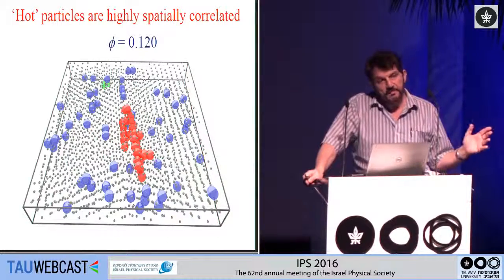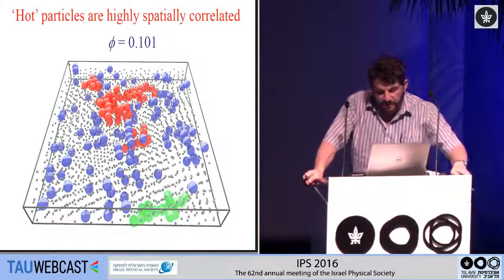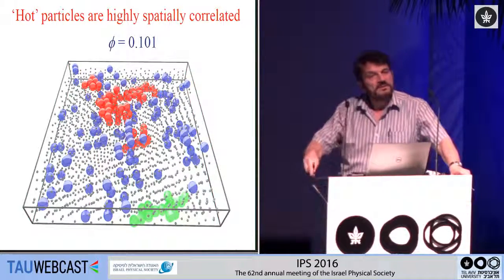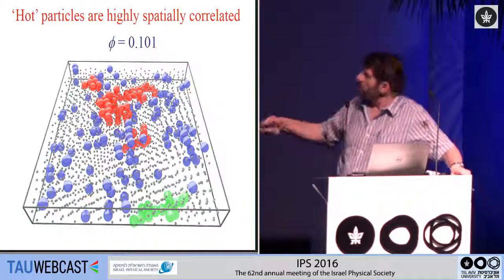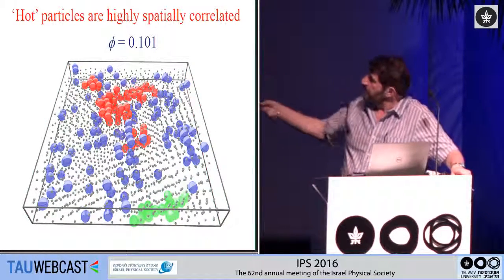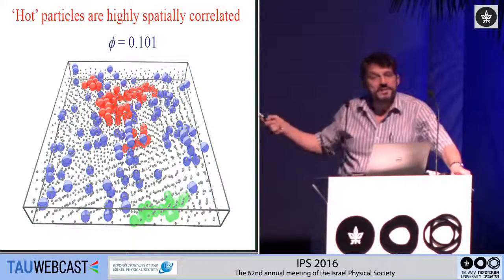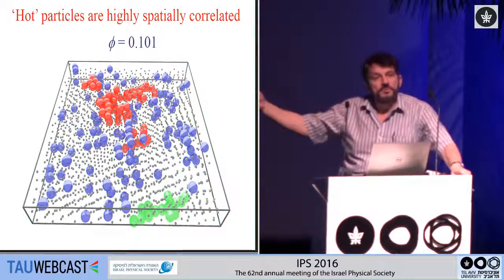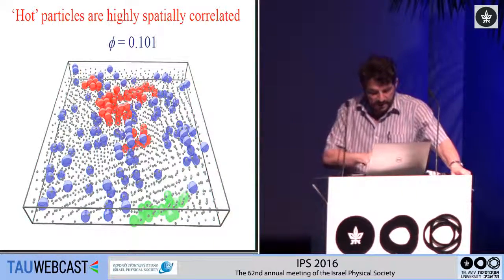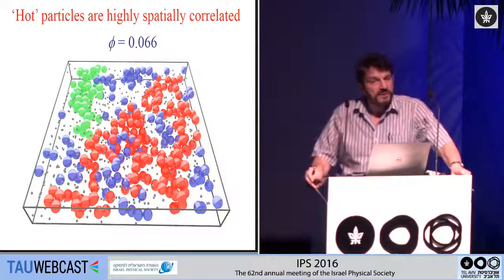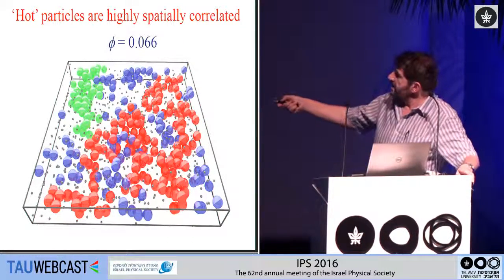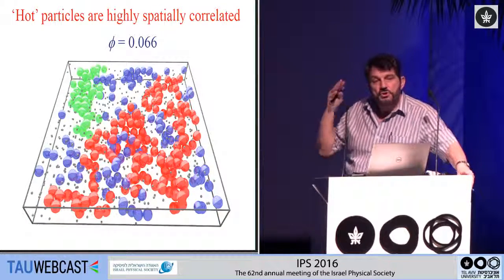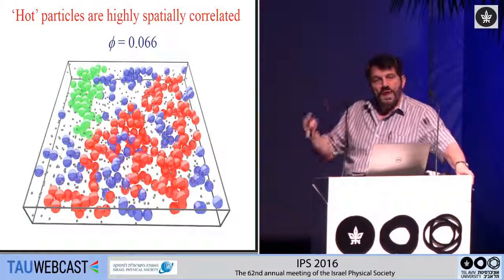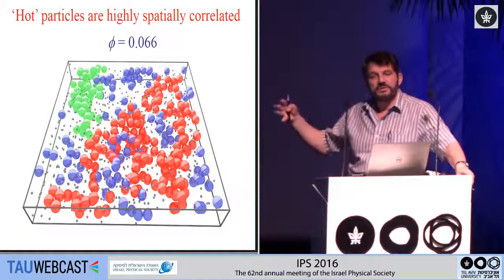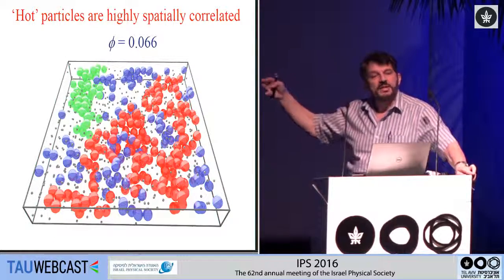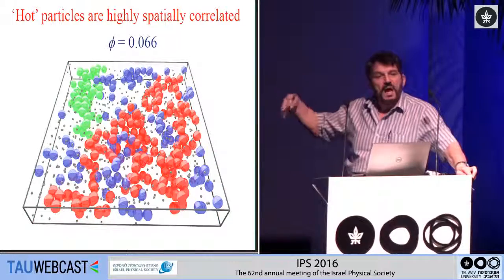However, as you further heat the system, that is, lower its volume fraction, then you find that these superheated particles exhibit this very strong spatial correlation. The red are the largest clusters, the green are the next largest, the blue are the smaller clusters. You can start seeing this distribution of clusters, but there's a very strong spatial correlation. And as you come much closer to melting, you see that this spatial correlation persists and in fact grows. The particles don't exhibit a random distribution, but rather a very strongly correlated distribution, with some very strong extended connections between the superheated regions.